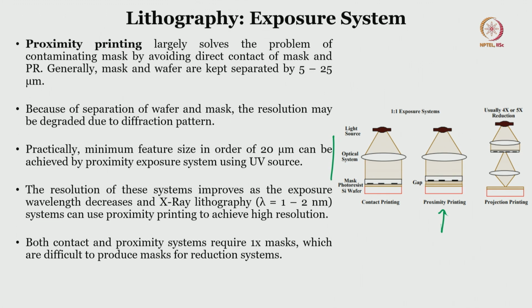The resolution of this system improves as the exposure wavelength decreases. That is when we go for X-ray lithography, where the wavelength is 1 to 2 nanometers and can be used in proximity printing to achieve higher resolution, because general resolution is poor, but if you use X-ray, then it becomes better. Both contact and proximity printing require a 1x mask, as it is difficult to produce masks for reduction systems.